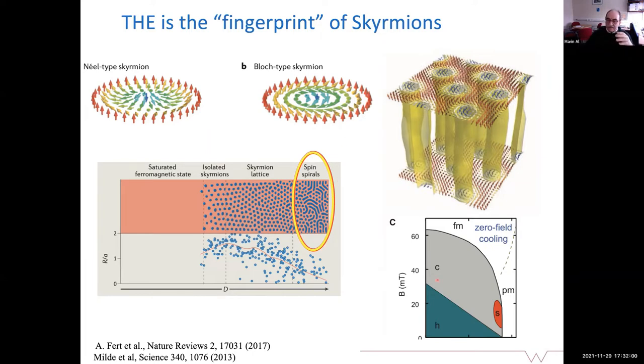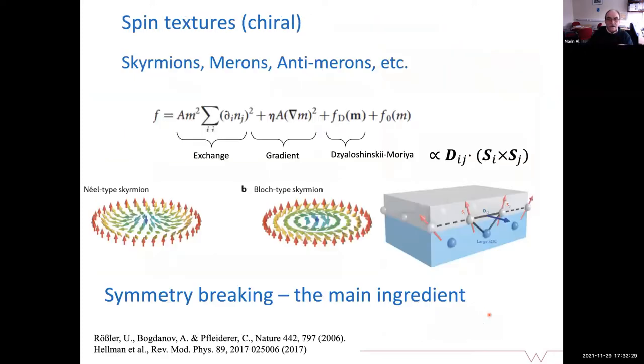So nevertheless, the more stable phases are chiral phases like the cycloidal phase and helical phase, which were known before skyrmion phases. Anyway, there is a phase transition, and this skyrmion pocket is usual in skyrmion crystals, in which these skyrmions occur usually due to the Dzyaloshinskii-Moriya interaction.